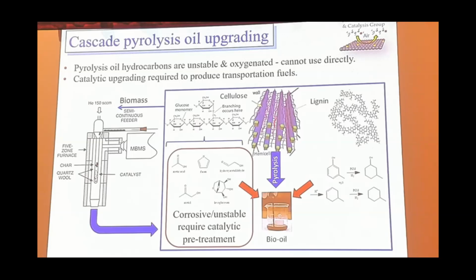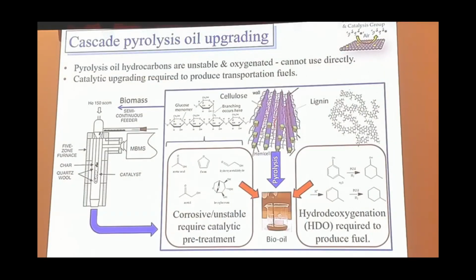It's comprised of short chain reactive molecules like acetic acid and aldehydes and so on, furanics, and then also phenolics that come from the lignin component. The problem is all these small molecules make it really unstable. And the acetic acid, for example, makes it corrosive to catalysts. So when you try to do HDO, you've got acetic acid there, it could potentially deactivate your catalyst. So really what we need to do is a pre-treatment that will remove some of these small components, and then also maybe try to do some chain growth, things like alcohol condensation to improve the hydrocarbon yield. And then once it's stable, treating the oil, then you can do the HDO.